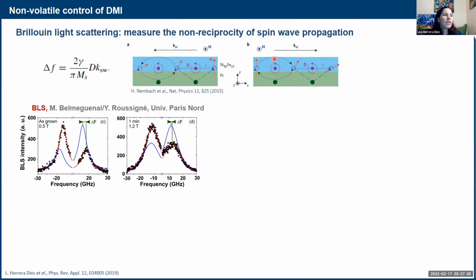So if you have these two spin waves going in different directions, they won't have the same frequency if there is DMI. The one that is going with the sign of the DMI is not going to be equivalent to the one going against. So this is going to generate a shift in the frequency of these two types of spin waves. And this is what we measure to get an idea of the value of the DMI. These are the typical spectra that we get.